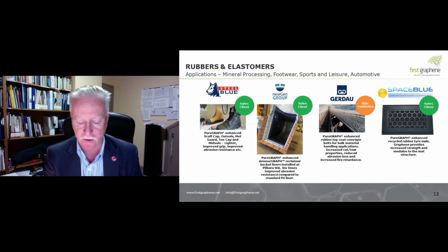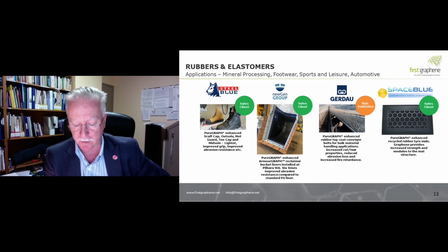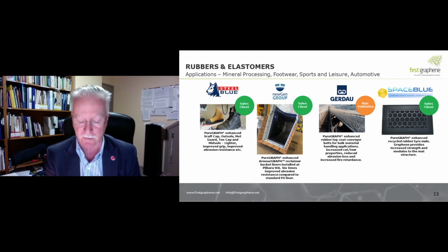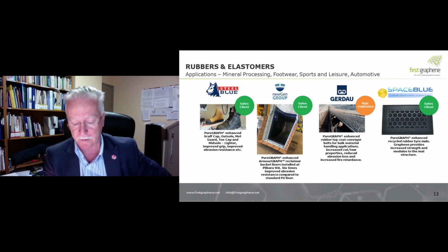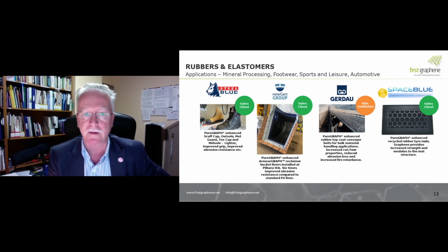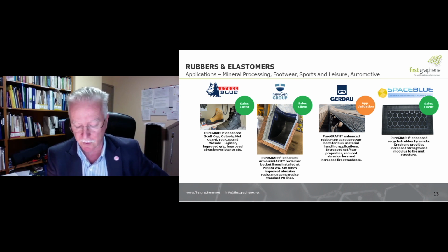We are selling to NewGen, which is adding graphene to polyurethane sacrificial liners in bucket wheel reclaimers on iron ore projects. Extended field trials have shown that with graphene, the liners last 6 times longer. Up until now, they generally have lasted 6 to 9 months. But with graphene, they could conceivably last more than 2 years. Maintenance downtime is the enemy of the high-volume iron ore industry in the Pilbara, which moves 1 billion tonnes of iron ore per annum. Rio is very keen to adopt these new liners.